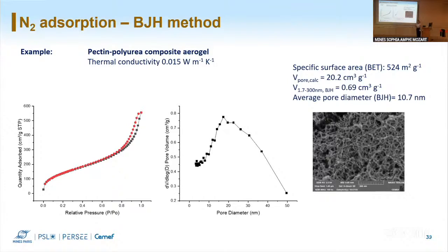We are in discussion with the company, and even they don't know. We are trying to understand if it's a problem with the technique or the method. It is a problem in general for bio-based aerogels, so for cellulose, pectin, I guess for all bio-aerogels. If you just look at the volume, you can take the value at relative pressure equal to 1 and convert your adsorbed nitrogen in STP into a volume of pores. That's quite direct. So probably it corresponds to 0.7, but then I don't know where the last 19 cubic centimeters went.